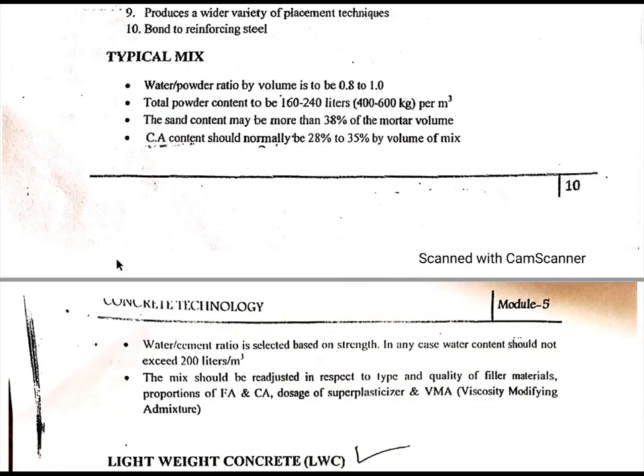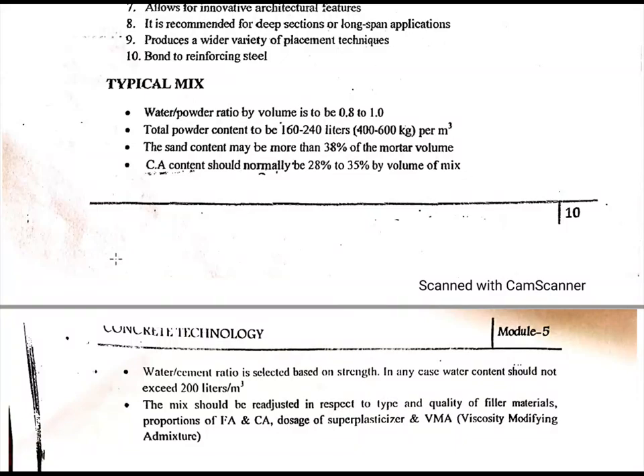So a typical mix of SCC contains a water powder ratio of about 0.8 to 1, and total powder content of 160 to 240 liters. One thing I have to tell: when you compare the ratio between the fine aggregate or powdery content of the concrete to the coarse aggregate, the fine aggregate or powder content is very much higher when compared with coarse aggregate. Coarse aggregate is less, and powdery material or fine aggregate is more than in normal concrete. In normal concrete, coarse aggregate is actually more.